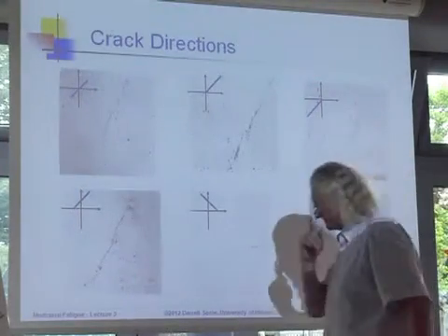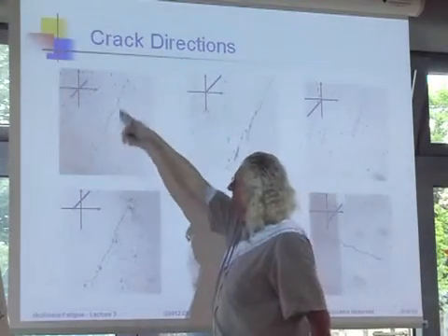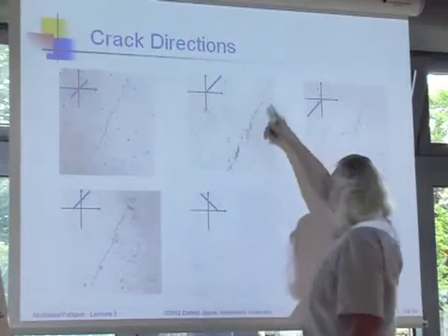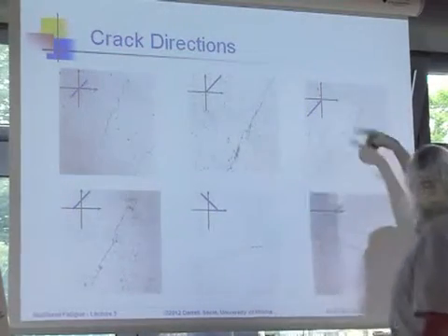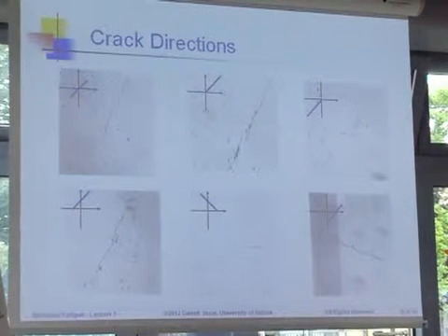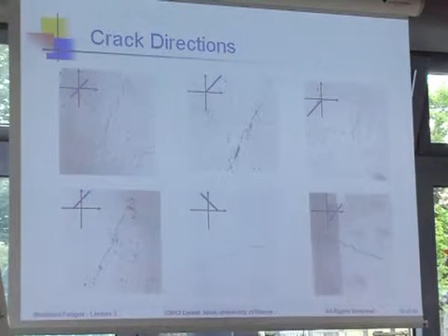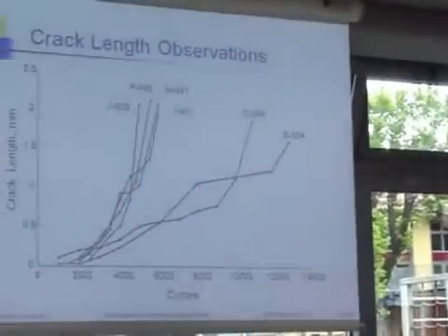And here you can see all those cracks. As I mentioned to you, all those cracks go like that. You find a single crack here, you don't see anything there, and so on. So what's really important is maybe shear strains acting on this plane, and whatever kind of stresses try to open it. But it's the real stress on one of the two shear planes. Okay, so that's what you get.